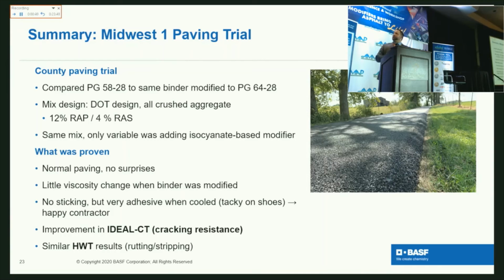Again, there's little viscosity change when the binder is modified. There's no sticking with this material until it cools down. One thing interesting there is Phil and I were walking along the mat. As it cooled down, you could walk on it normally, and then as it cooled down further, I'm not sure what the temperature was, it started to get more tacky. So your foot would stick excessively compared to what is normal. And so again, like I was saying earlier, it's an adhesive. So it's a glue. It's not just an elastomeric adhesive or an elastomeric glue. It's a hard glue. And then once it cooled off, it was, I mean, essentially like a rock.